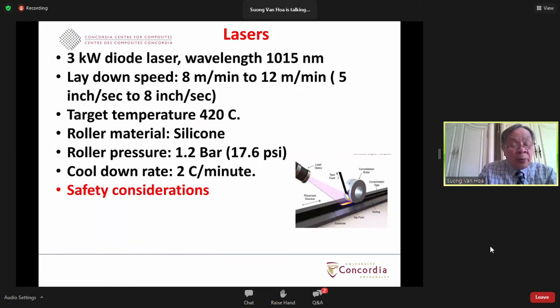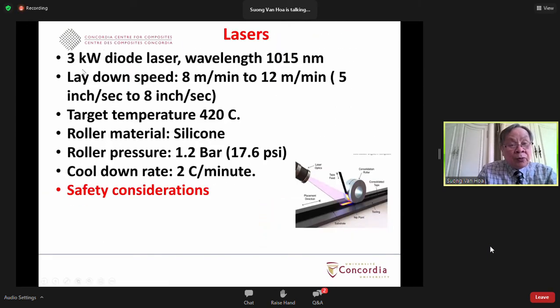Laser, quite a few machines these days use laser. The power of the laser can vary anywhere between 3 kilowatt to 5 kilowatt diode laser. The wavelength is about 1,000 nanometer. The speed can be fast, from 8 meter per minute to 12 meter per minute. And one of the advantages of the laser is that they can use a soft roller. That is a case made of silicone. And the fact that you use a soft roller like silicone allows a larger area of contact between the layers of the composite. And that way you probably tend to have a good interlaminar shear strength. However, the disadvantage of the laser is safety consideration because of the fact that the heat is strong and you need to make sure that it doesn't hit the operator during the process.